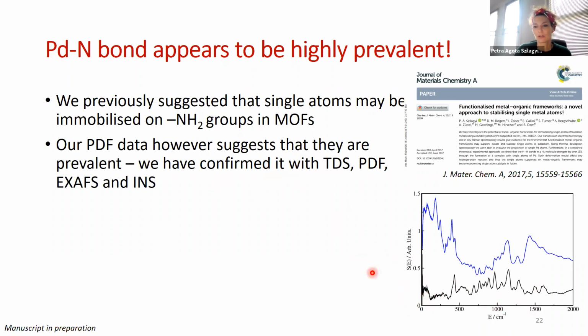This is inelastic neutron spectroscopy still, and if you're looking at the low energy range here, then what you can see in blue is the spectrum of the empty framework, and in black you see the spectrum of the palladium loaded framework. And what you see is what's happening when the palladium is added inside the pores of the framework. This is accompanied by the disappearance of loads of modes. In fact, many of them remain, which tells us that the framework is still intact, but many of the low energy modes, which can be associated with rotation modes, for example, disappear.